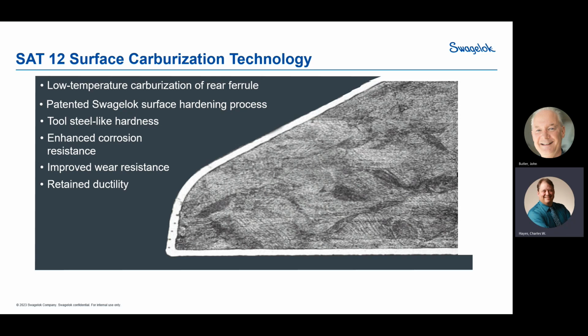What you see here in white. That hard surface is like tool steel, so it's able to cut into tubing and get that very good dive that we get for our tube grip. Finally, it has enhanced corrosion resistance, so it's actually even better in corrosion than an untreated ferrule. It gets great wear, but most importantly, one of the really, really important things here is that it does retain its ductility. So it does not crack when that ferrule is moving and diving and reshaping itself through its plastic deformation phase to get to the final grip onto the tube.